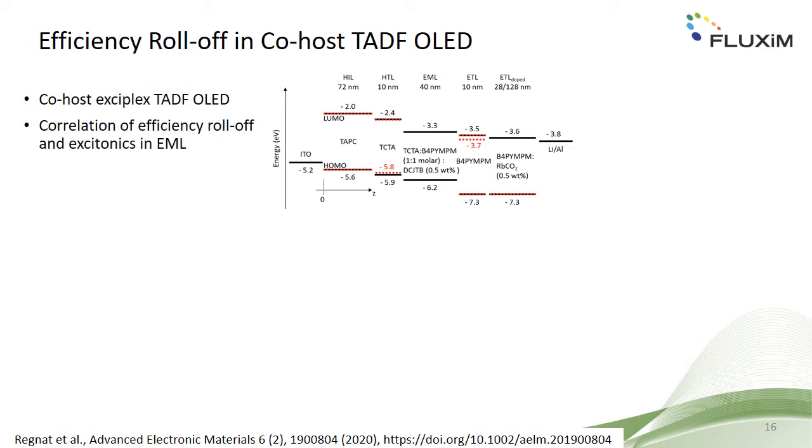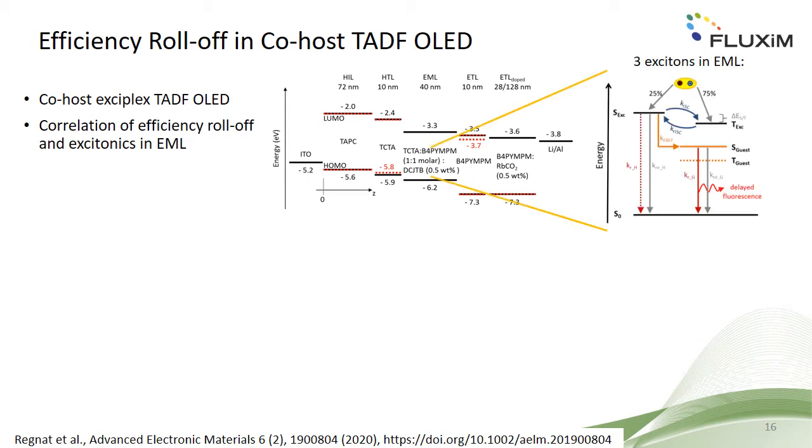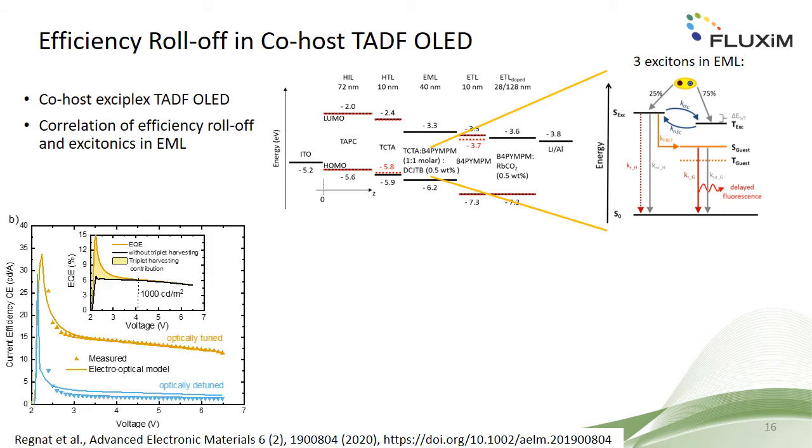Whereas in the previous example of a phosphorescent OLED, we only modeled one exciton, namely triplets representing the emitter molecules, now we look at a 5-layer TADF OLED containing an emitter layer with a co-host and a fluorescent dopant, DCJTB. The TADF mechanism is realized in the co-host. Their triplets experience reverse intersystem crossing due to thermal activation, and there's a resonant energy transfer to the dopant. So we model 3 types of excitons in total.